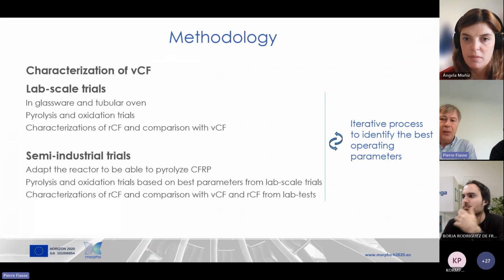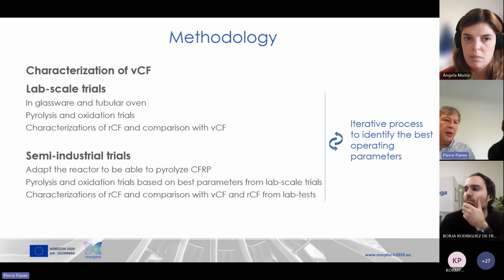So what is the methodology? The methodology was first to start from a virgin carbon fiber and to characterize this fiber, then to compare with recycled carbon fiber. So the first part of our work was to perform lab scale trials in glassware and tubular oven with pyrolysis and oxidation trials to deduce the optimized time and temperature for pyrolysis and oxidation. Then characterize the recycled carbon fiber to obtain the optimized parameters. And it is an iterative process. Then we did it on semi-industrial level. So we'll pass now the floor to my colleague, Xavier.